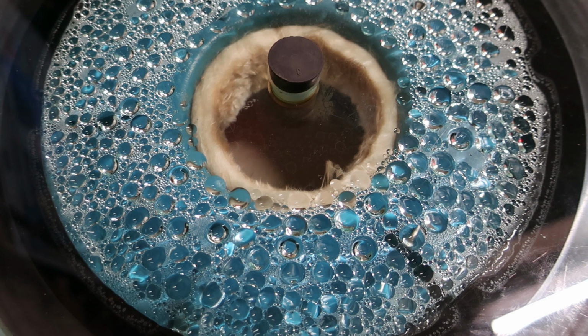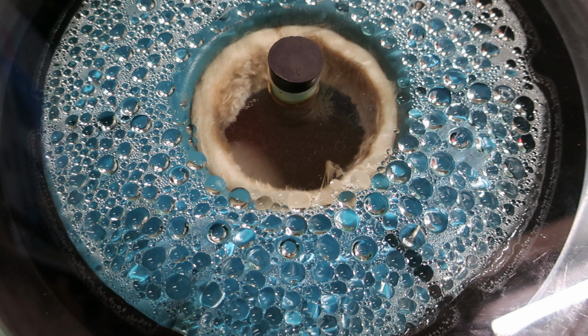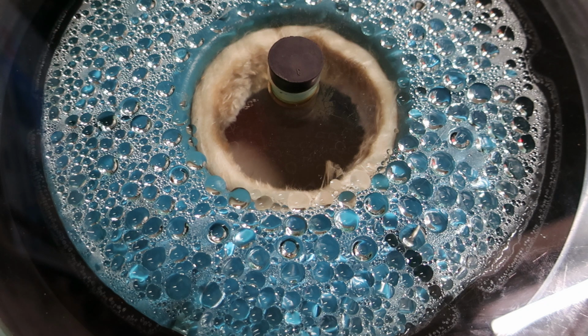But I do see it where you've got a bucket of zeolite and you've put it in and the center doesn't get up to temperature and doesn't release its moisture. So bubbling air through it or stirring it or pouring it out and doing it again and again is accomplishing that for you. But I think you're getting the same thing by having smaller batches for longer periods of time and just allowing all the zeolite to get up to temperature and have that wonderful opportunity to give up some of its moisture. Now I could be wrong, probably am, but that's how my brain looks at it. I think that makes sense to me.